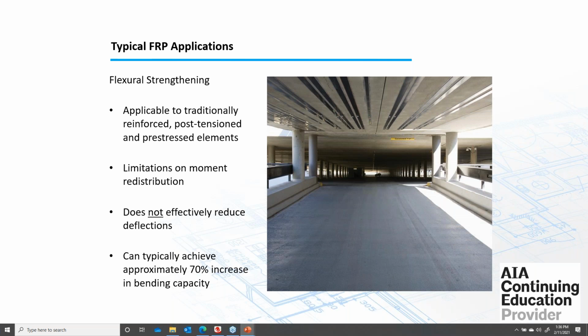As far as a rule of thumb, if you're looking at a project where you have to do some strengthening and you want to get a rough idea of whether FRP is possible, the first thing you'd have to do is check those equations that I showed previously to make sure that you can carry the service load without the FRP. Assuming that you can, we can generally increase the strength of the existing member by about 70% in bending capacity.